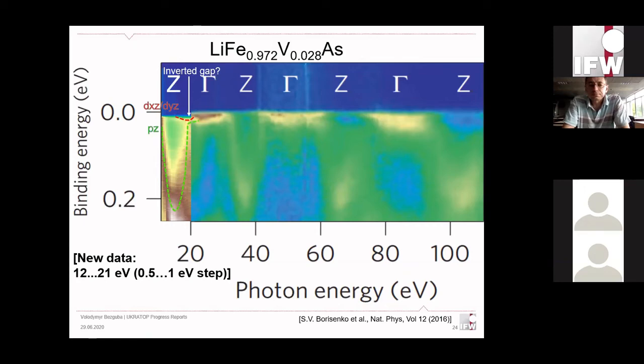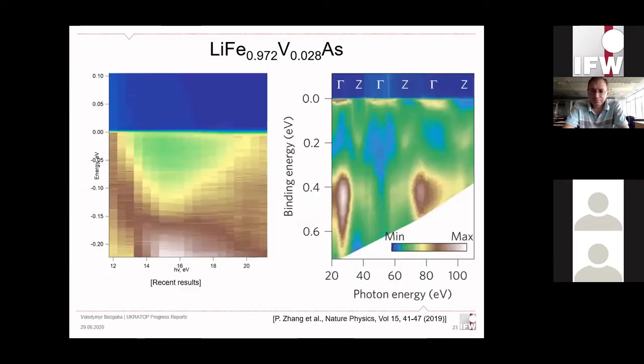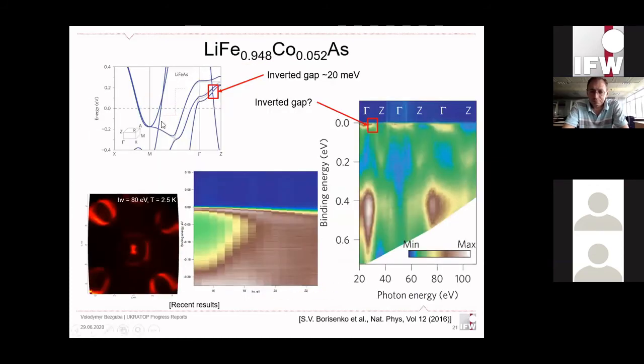It does shift it. This is still being prepared for publication, so it's a rough picture just for the presentation, but it's about 10 to 15 milli-electron volts of shift, and this is even with low saturation of vanadium in the compound. The bands really change at the Fermi surface with doping. Unfortunately, I don't have them in the presentation. I have only the Fermi map for the cobalt doping.